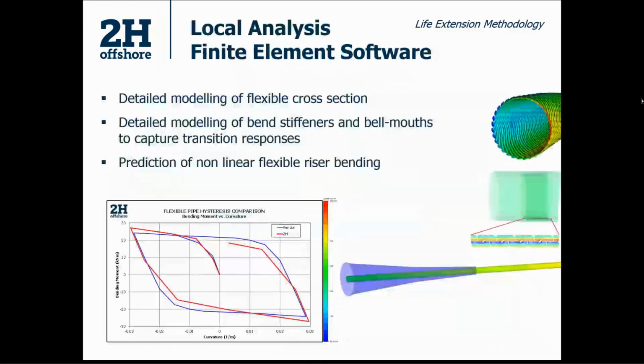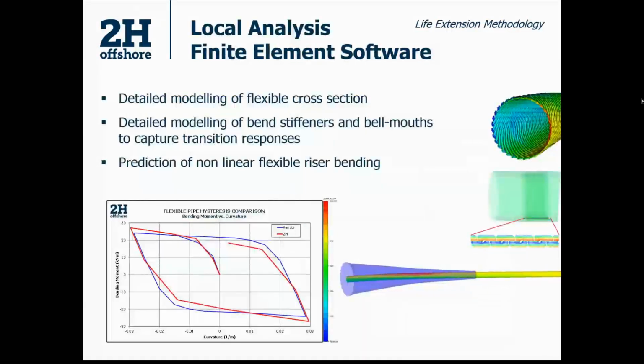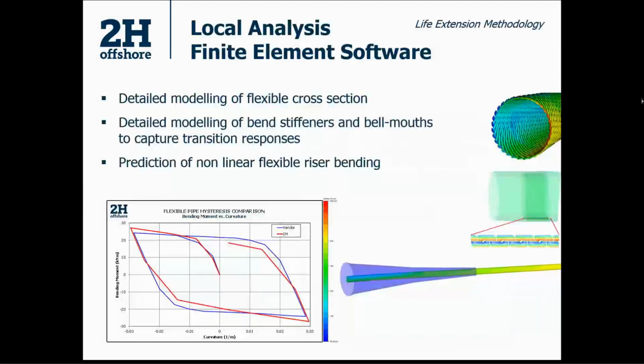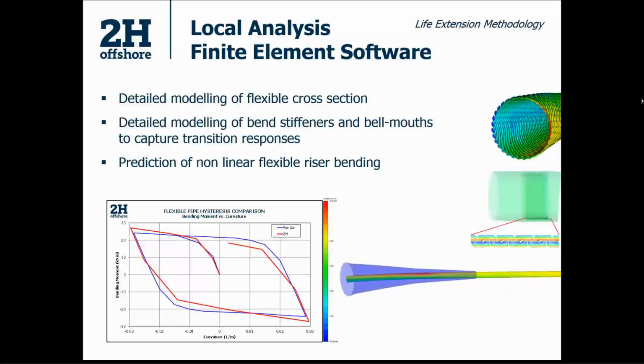A little bit more detail about how the local analysis is done. It's going in and doing a detailed modeling of the cross section. So each of the layers are modeled with the primary focus being on the carbon steel components, because they're the layers that are most prone to fatigue. It is possible that the other layers will be the limiting factor, but generally it is the steel components. We're going to model the transitions in more detail. So things like, as I mentioned before, bend stiffeners, bell mouths. That transition response is really important. And here is where we're going to start to look at the hysteresis effect. So that plot in the left-hand corner is the plot of how the bending stiffness changes based on the combinations of bending and tension. And we're going to do this in an iterative approach, and I'll talk about this on the next slide.